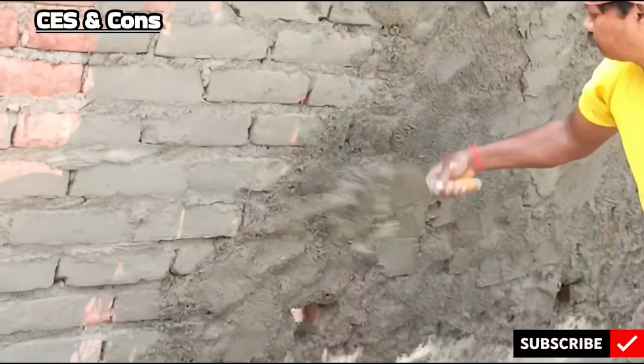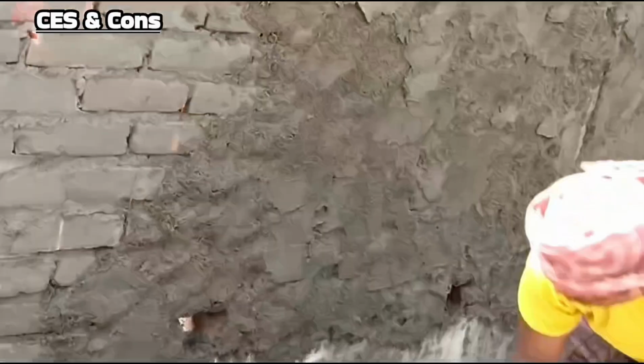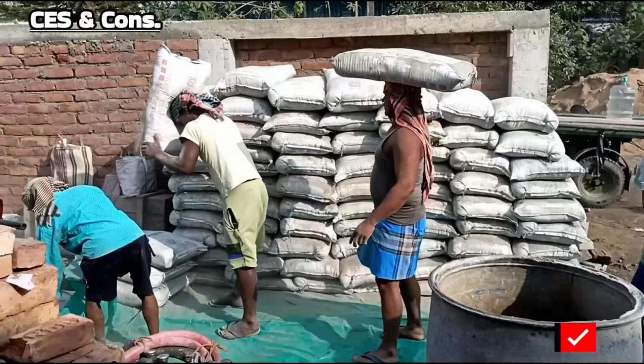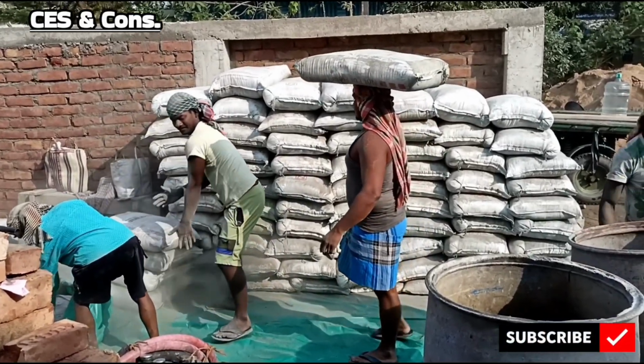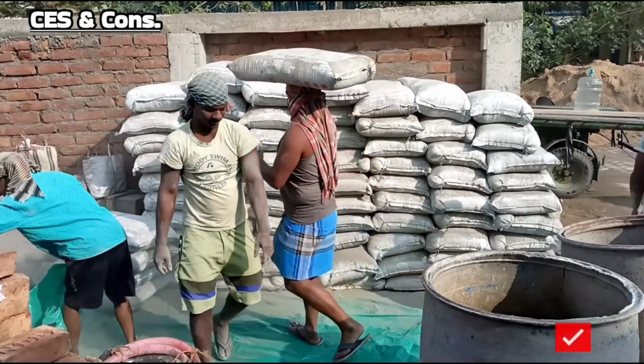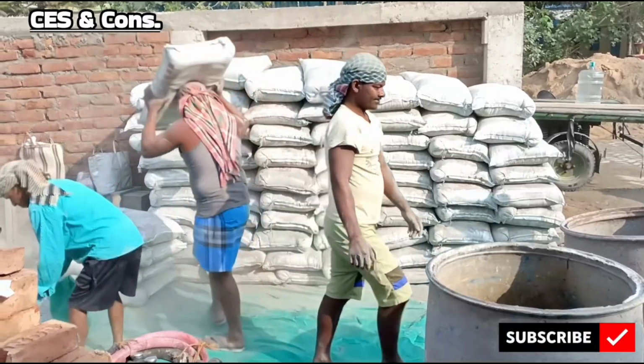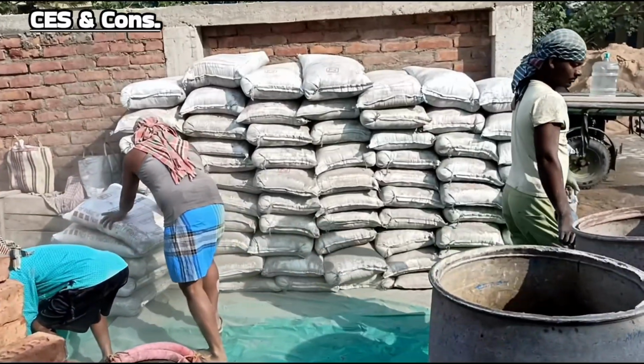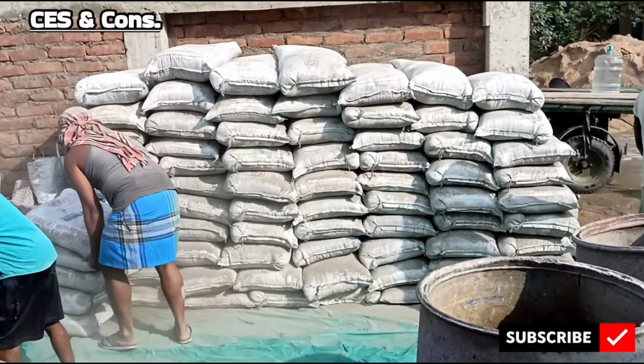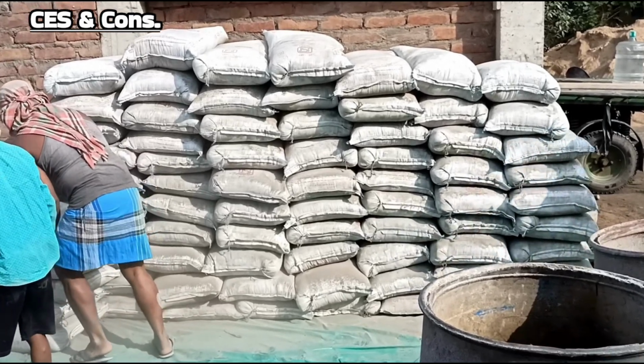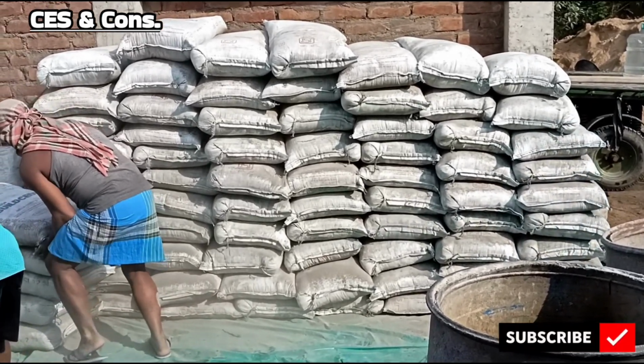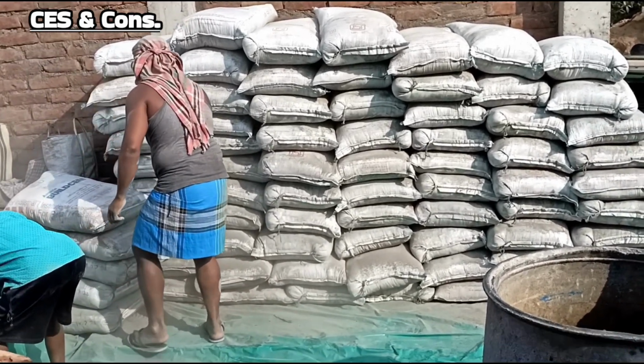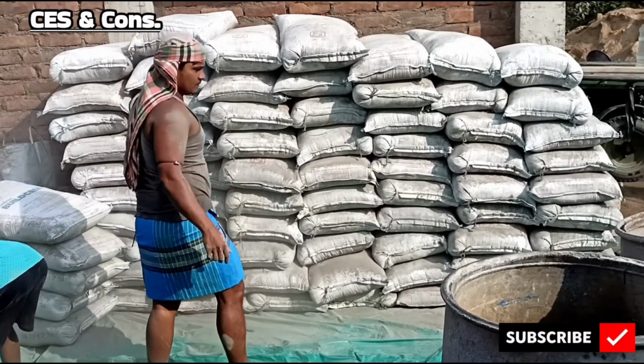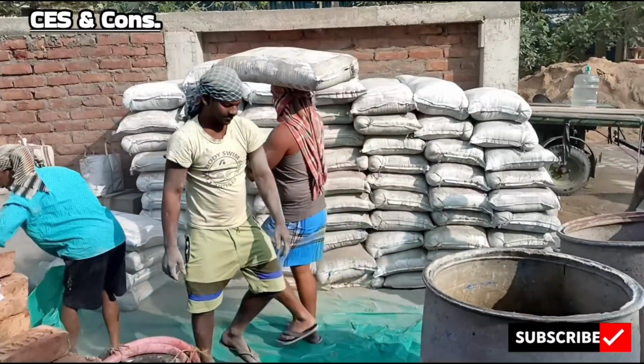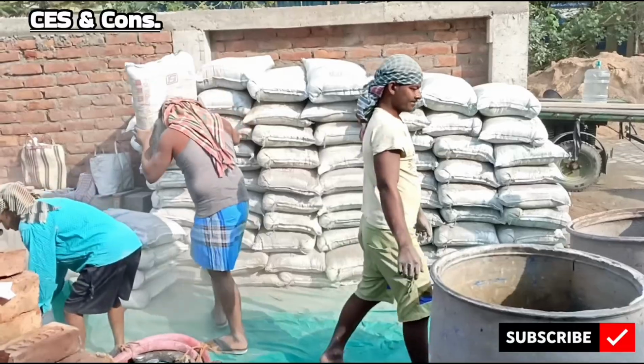Friends, now going to the specifications of the materials required in this work. Cement. Ordinary Portland cement conforming to IS 269 or IS 8112 or IS 12269 may be used depending on the grade of cement requirements. Portland Pozzolana cement as per IS 1489 or Portland slag cement as per IS 455 is also permissible to use.